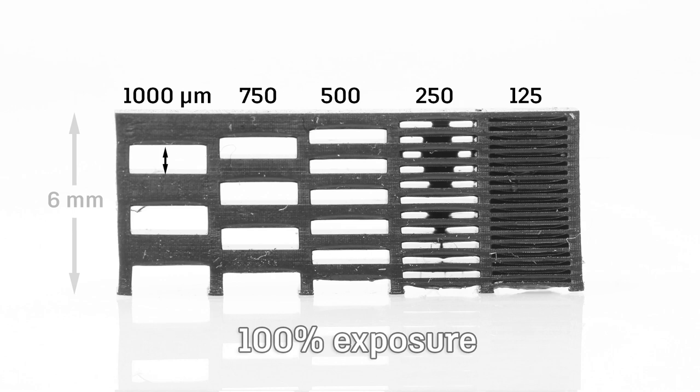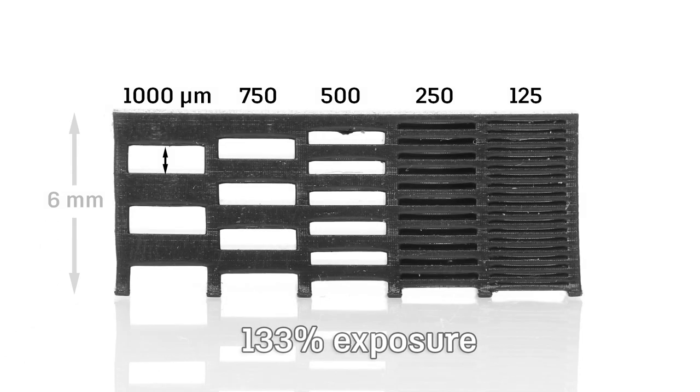The 250 micron gaps are partially resolved, but the 125 micron features are completely filled in. If we add just 33% more light exposure, the 250 micron features are completely filled in, and we have effectively lowered our resolution.